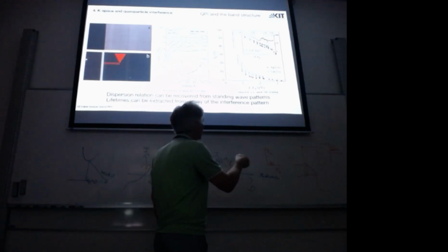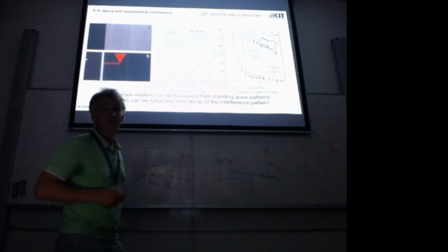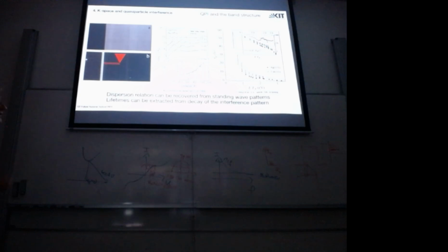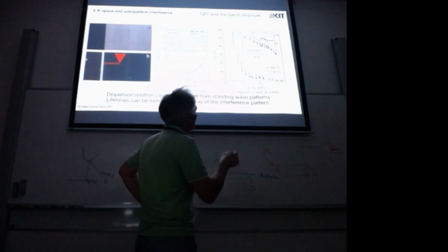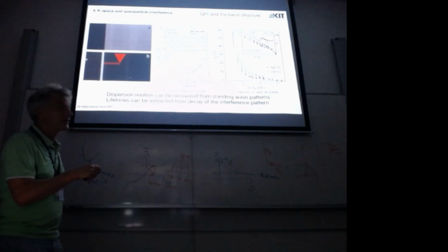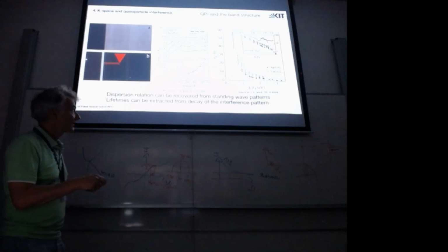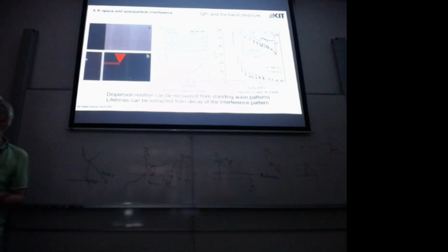These are the measured data points. And this is 1 over E squared. This is Fermi liquid theory. So you see, this looks pretty nice. This is a Fermi liquid. And indeed, in a double logarithmic figure, you can see this slope here is proportional to 1 over E squared. So the particles with very low energy live very long. The particles with high energy scatter all over the place, and electron scattering is happening here. And they decay.